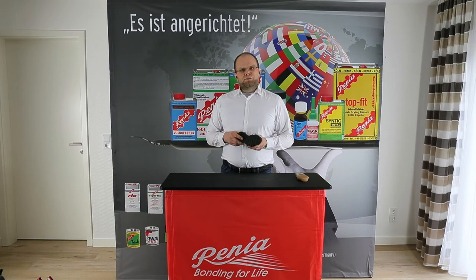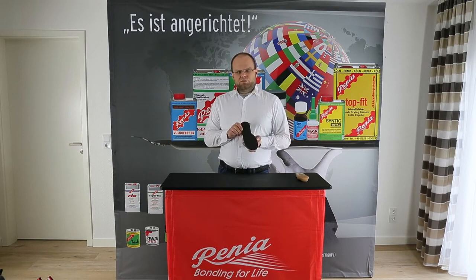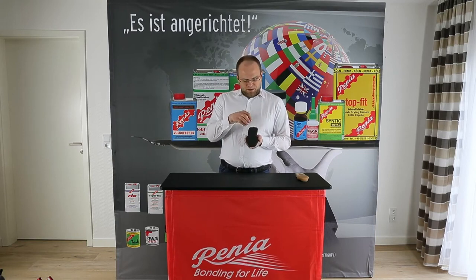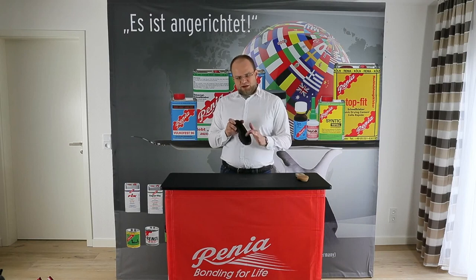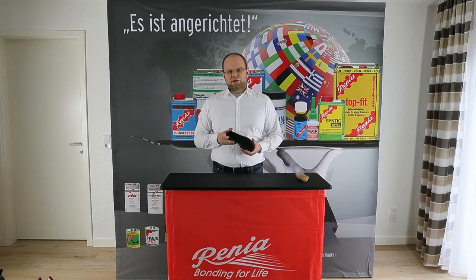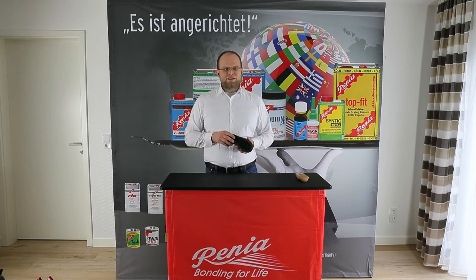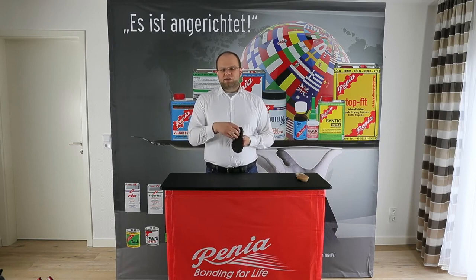The first thing you do, you grind the sole. You do that anyway. If during the grinding process you actually grind into these chambers here, into this honeycomb structure, that's a very good sign that it is very likely TPR, because rubber just doesn't show this kind of structure. Rubber soles aren't made that way. So that gives you a first hint.